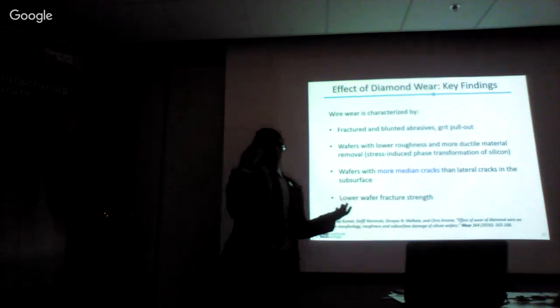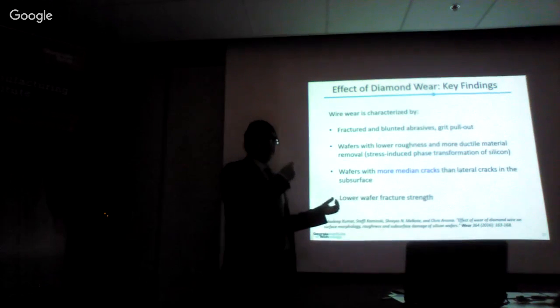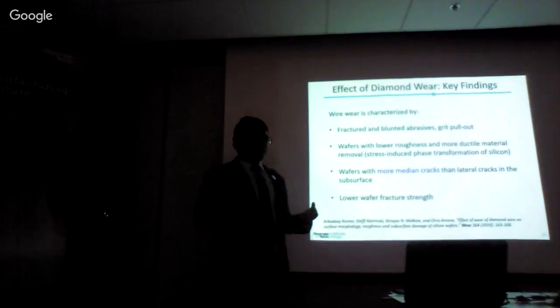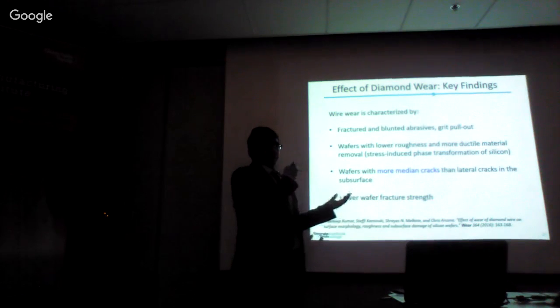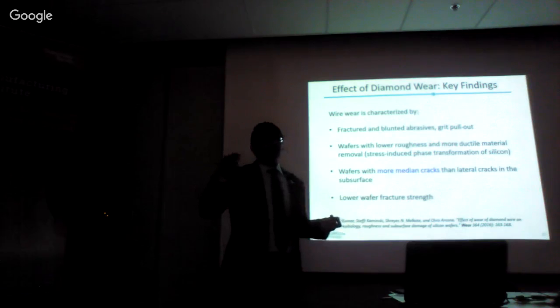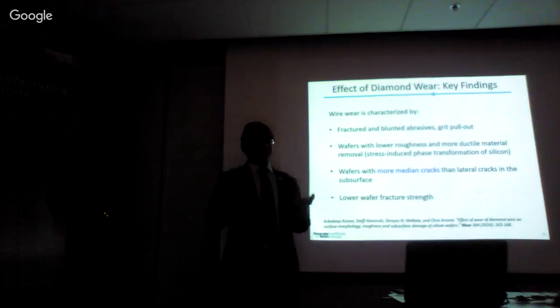In summary, the key findings from this task: with wear of the abrasive, we see fractured and blunted abrasives, and even some of the abrasive pulled out or lost. And this affects the force per abrasive, as I was speaking about in the previous slide. And the force per abrasive affects the micro cracks, being median cracks or lateral cracks. But with wear, the wafers are formed with lower roughness and more ductile mode material removal because of stress-induced phase transformation of silicon. But that's just the story on the surface. If we dig deeper into the subsurface, we find the wafers have more median cracks than lateral cracks when cut by the used wire, which reduces the fracture strength of the wafers.